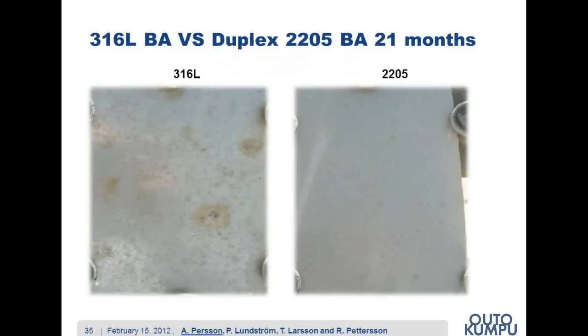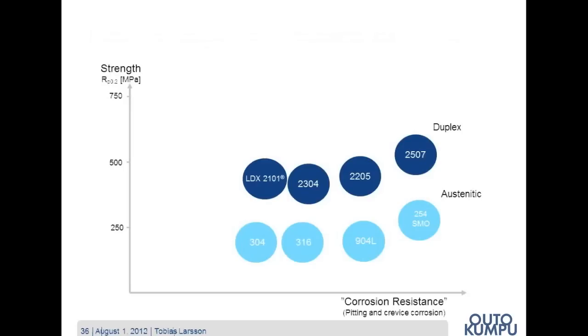So we can clearly see from the 21 months results that the duplex grade 2205 performs better than the Austenitic grade 316.